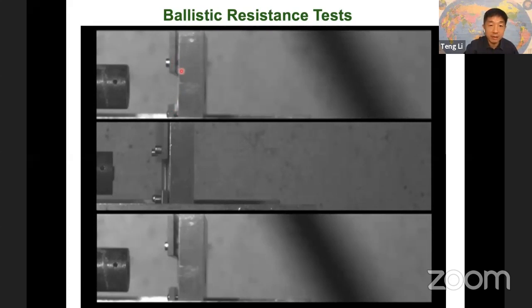You cannot really see. On the next slide, we have another Phantom camera from the back, from the side. You can see the wood samples. So this one is the natural wood piece here. This one is a monolayer of super wood. And the bottom one has five layers of super wood with alternating orientation, 90 degrees away from each other. But we keep the thickness of all three samples the same. So you can compare apple to apple. So the incoming speed of the steel bullet is the same.